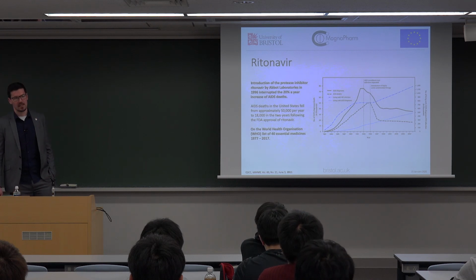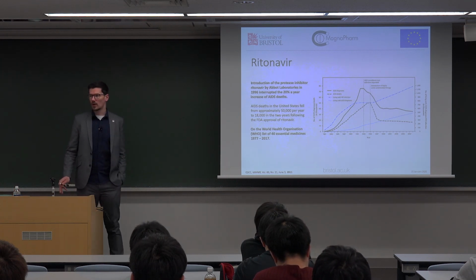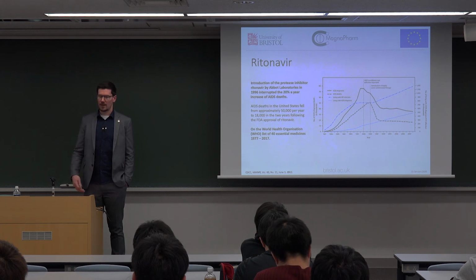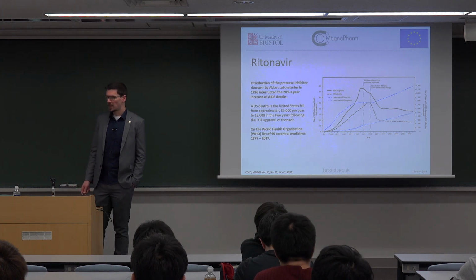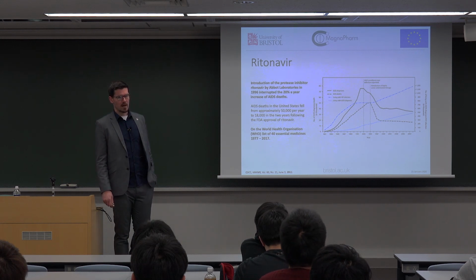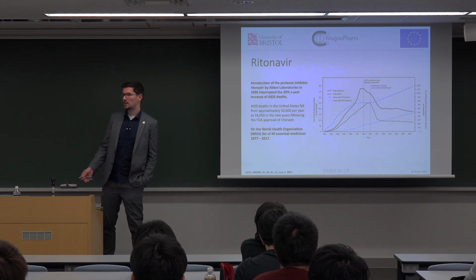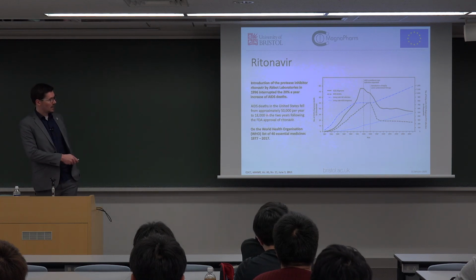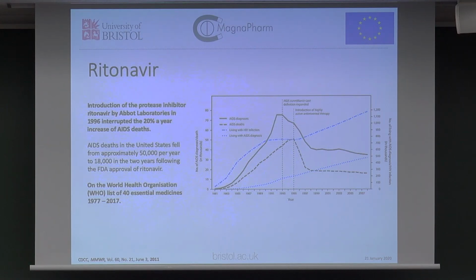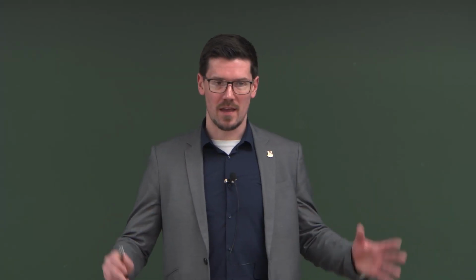A very famous case of this is that of ritonavir. Anyone that works in polymorphism or organic pharmaceutical crystal growth would have heard of ritonavir. It's a protease inhibitor that basically stopped people dying from AIDS. So if you look at the dotted black line in this graph, which is the important one, that's the number of deaths from AIDS, the disease. And when ritonavir was released, you see this drastic decline. It went from 50,000 deaths per year to 18,000 deaths per year. So people can then live with AIDS without it being a death sentence. So it was a big thing.